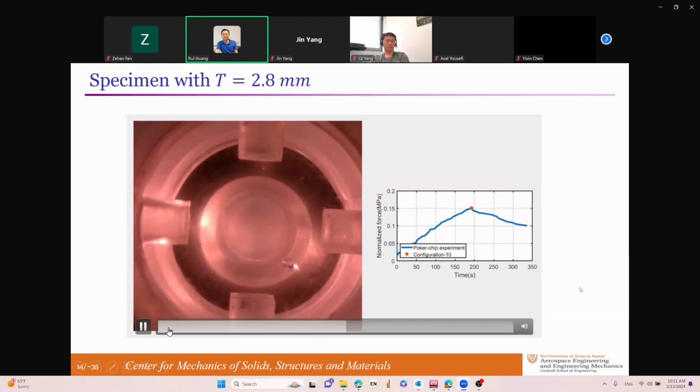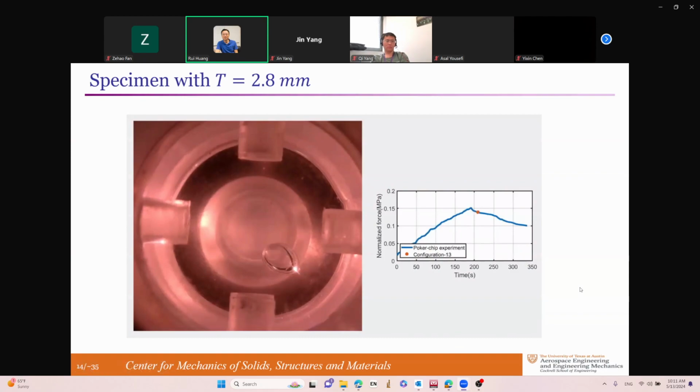And if you were observing through that, we saw something nucleate here. This is completely in the interior of the specimen, where there was no visible, optically visible prior flaw, and it continues to grow, approaching the symmetry of the object with a crack in the middle of the diameter of the specimen. One crack, interior nucleation. But I don't know whether it's nucleated entirely in the interior or whether one of the interfaces is a delamination, right?